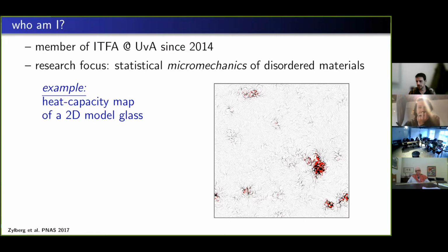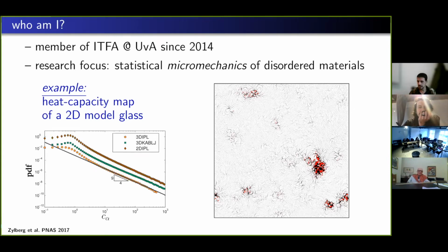What I'm showing here is the spatial map of the specific heat of this glass. And what you can see is that there are red and black contributions that come from the various interactions between underlying particles in this 2D system. And you can see that there are these excitations that are localized that carry most of the heat capacity of the system. We all know that equipartition should normally hold and that every normal mode contributes kBT. But the spatial arrangement of the contribution is something that highlights the defects and the excitations in the glass. I was also busy studying the statistical properties of these fields. And so this is why Parisi's work is also highly related to what I do.